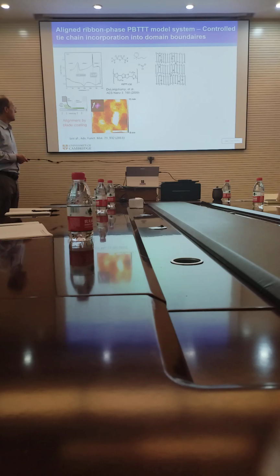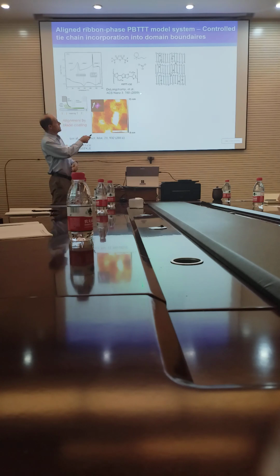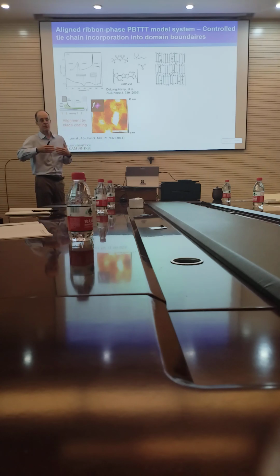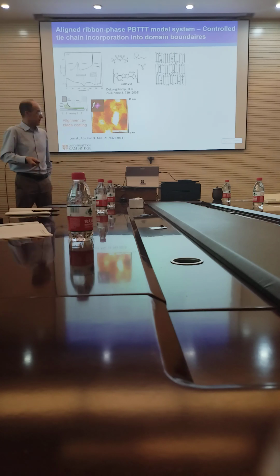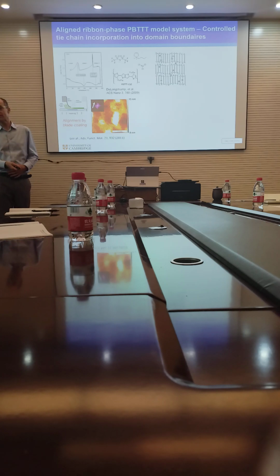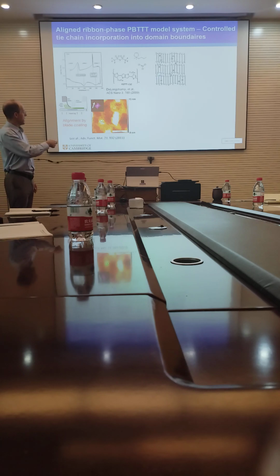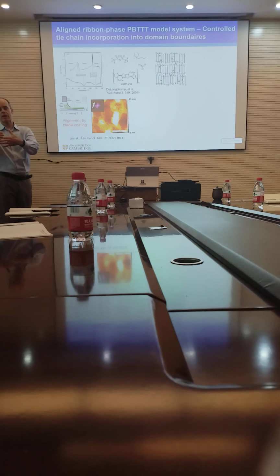If you do an AFM microstructure image, or an atomic force micrograph, you see these ribbons, they look like spaghetti running from left to right. And each of these ribbons is a little polymer crystal, and the dark regions in between are those domain boundaries. So every 60 nanometers or so, you have one of those domain boundaries, and then you enter a new polymer crystal. With a blade coating technique, we can align these ribbons. So we have essentially films where we have the polymer chains all aligned in one direction, the ribbons running all from left to right, the polymer chains running from top to bottom. And then we have a very regular structure where you have crystalline domains, the domain boundary, crystalline domains every 60, 70 nanometers.